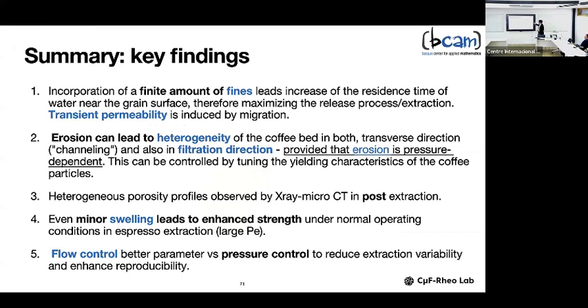The take-home message here is that fines, the small particles, are really important because they can produce time-dependent effects on the permeability, and it also increases the strength because they slow down the flow rate and therefore increase the residence time of liquids near the solids, and therefore they're important as a parameter for increasing the strength of the coffee.